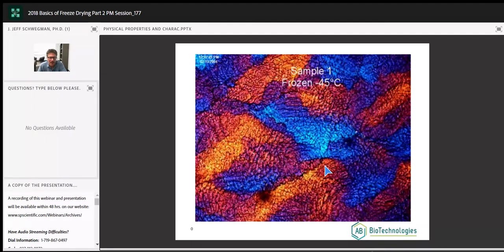Let's take a look in amorphous phase. We freeze the sample down. Now, what you'll see here, this is all the same sample. The differences in color represent our field of view to what end of the crystal, the birefringent crystal, we're seeing. So say we see blue, we're seeing this face of the crystal. Say an orange, we're seeing this face of the crystal. Maybe a red, we're seeing this face of the crystal. So it's dependent on our field of view to how the crystals have formed in our frozen sample.